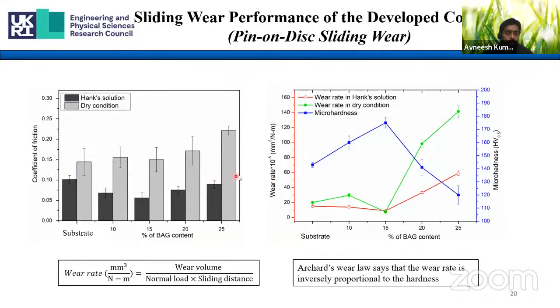Similarly, for coefficient of friction, usually it is independent of all these things, but some literature says that coefficient of friction depends on contact area. So here, the maximum coefficient of friction is in 25% baghdadite and the minimum is in 15% baghdadite. It is because the bonding was relatively loose in 25% baghdadite. As you can see, the hardness value is also very low, which indirectly tells about the bonding also. Because of the severe plastic deformation, the wear debris are very high in this case, which we will see in the post wear analysis.